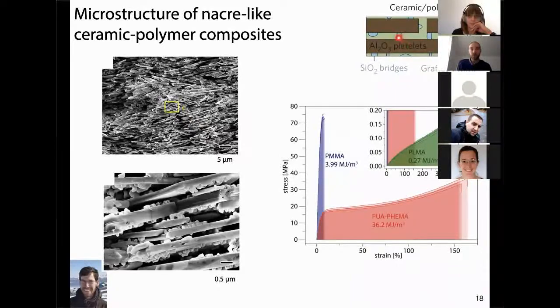The microstructure, the cartoon, has these very long platelets. We have silicon oxide, so mineral bridges in between. We can control the amount, and during the heat treatment you would form these mineral bridges. And in between, we infiltrate a polymer as a secondary phase.